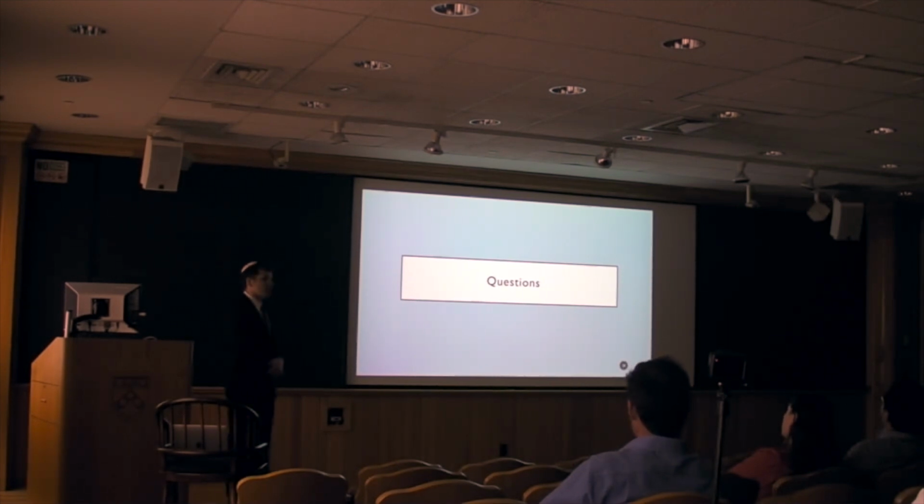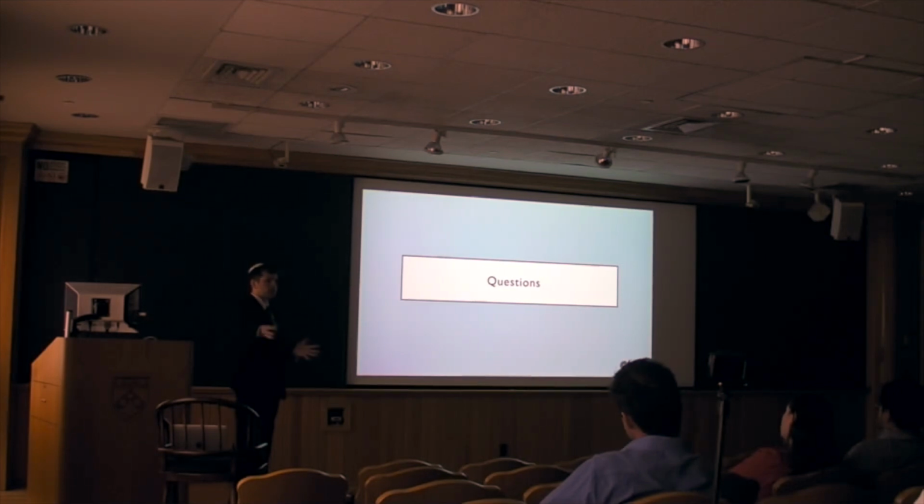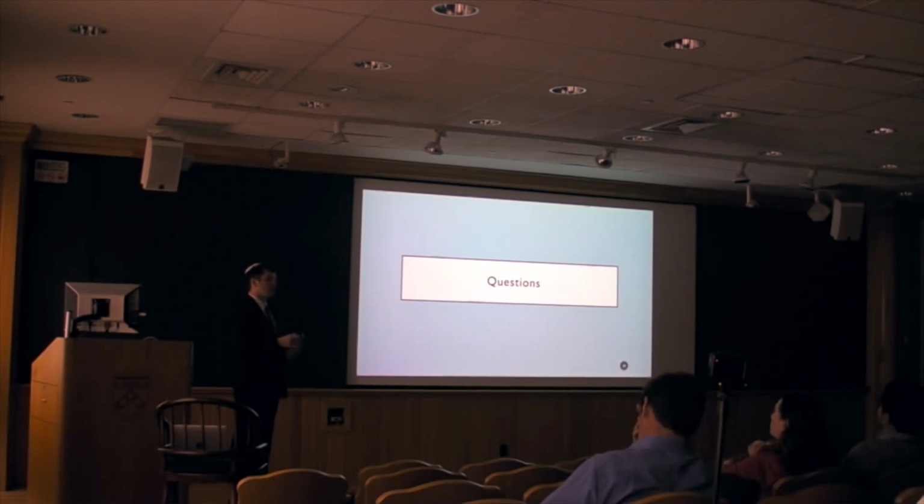Right. So I'll start with your first question, which is about the importance of charge descriptors in mapping chemical information to a property of interest. In principle, it's very important. And so in our catalysis work where I did machine learning, which was for the doping that induces chemical pressure, we found that charge on the atoms of the dopants nearby the active site can play a small role. However, the system is overall metallic, and so changes in charge farther away from the active site are going to be screened. And so there was a minimal electronic effect there.